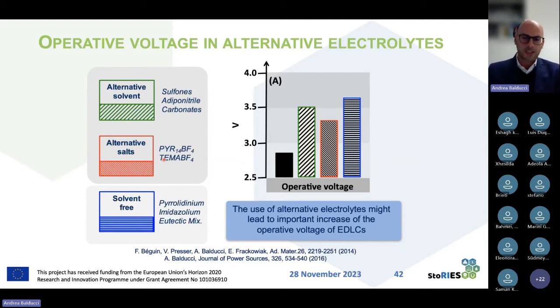So what you're seeing here is basically the operative voltage that can be achieved when we are using alternative solvent, alternative salt, or ionic liquid. And what you can see is that if the black is the state of the art, which we set to 2.8 volt, when we are replacing acetonitrile with this alternative electrolyte, we can indeed increase the operative voltage. So we can even go to 3.5 or higher.